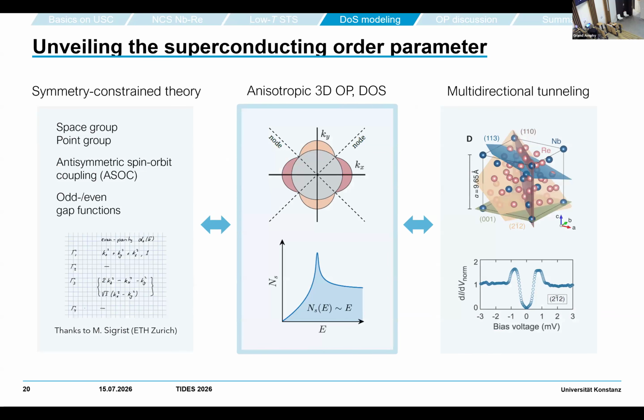And so we asked our theory colleagues, in particular Manfred Sigrist, for help. What do we know about the material? We know the space group and point group the material belongs to. We also know that we have antisymmetric spin-orbit coupling. And then we asked him to tell us which gap functions are possible given that symmetry. We know what we measure in the spectra, and the goal is to figure out what is the order parameter symmetry that is in agreement with the symmetry constraints given by the crystal structure and our experimental findings.